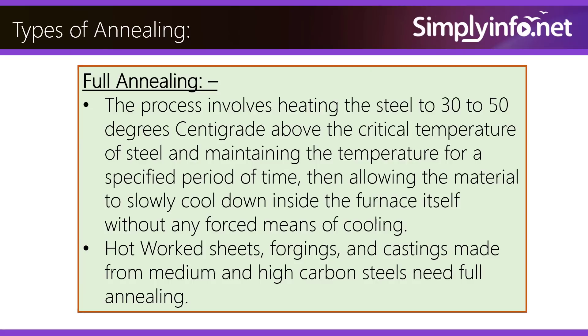Full annealing involves heating the steel to 30 to 50 degrees centigrade above the critical temperature of steel and maintaining the temperature for a specified period of time, then allowing the material to slowly cool down inside the furnace itself without any forced means of cooling. Hot worked sheets, forgings and castings made from medium and high carbon steels need full annealing.